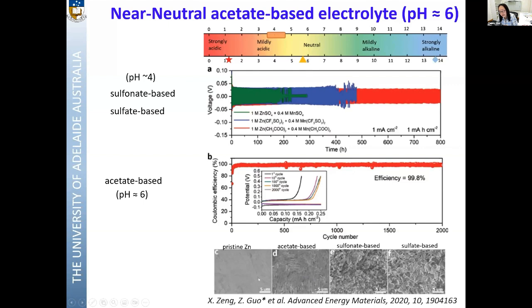You can see here the SEM images. This is a pristine zinc surface, quite smooth. This is zinc cycled in the sulfonate and sulfate-based electrolytes, you can clearly see the porous structure and dendrite formation on the surface. In the acetate-based electrolyte, after cycling, you can see the surface is still quite smooth, and the coulombic efficiency in the acetate-based electrolyte is much better, indicating the plating stripping reversibility is good.